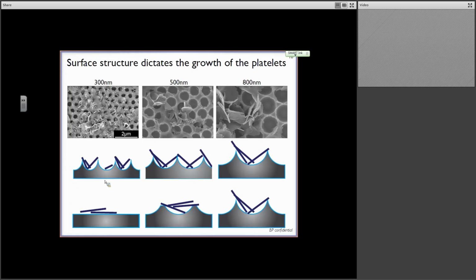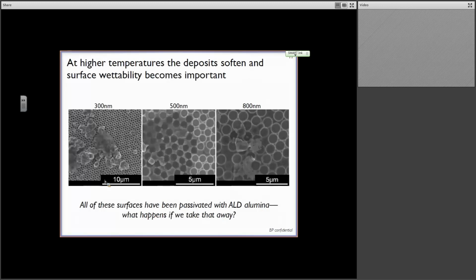Okay, so we can see that at relatively low temperatures, intermediate between room temperature and what we're going to define as high temperature, the roughness does play some sort of role. As we go to higher temperatures, we no longer see this plate-like morphology. These are the same three length scales in our deterministic structures that I showed you previously, and we don't see those plates anymore. We see more of a wetting behavior on the surface where we do see these deposits, and then on top of those filled-in holes, we start to see bigger clumps coming out. What this suggests is that wettability, once the asphaltene starts to soften, is becoming important.